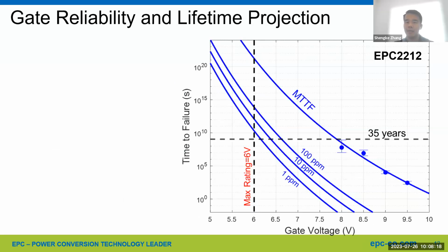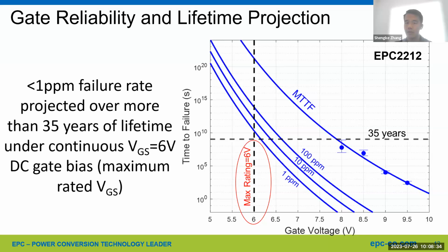The impact ionization model is plotted against the measured data points for EPC2212, where a good fit is found. If we keep the gate bias at 6 volt, the VGS max, we project less than 1 ppm failure rate over 35 years of lifetime under continuous DC bias. This projection is also consistent with our field experience.